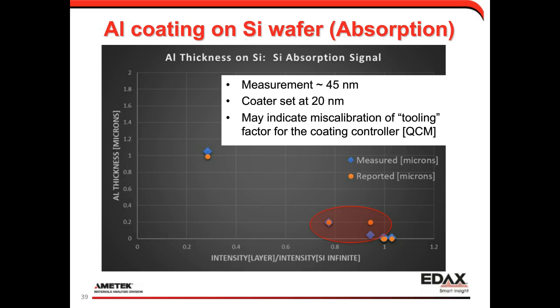But the monitor crystal is off to the side, whereas the deposition zone is in a different geometry in the system. There's supposed to be a tooling factor, a fudge factor, between the monitor position and where you are depositing material. So it could be that, where the coater is set up for, where we're getting 20 nanometers and measuring 45, there could be some miscalibration in this tooling factor. That's another factor the customer is going to look at as well.